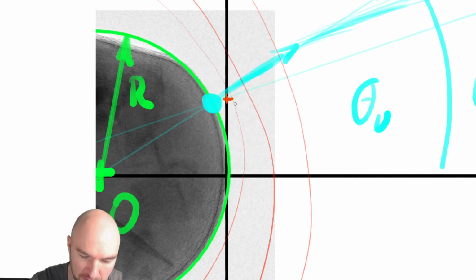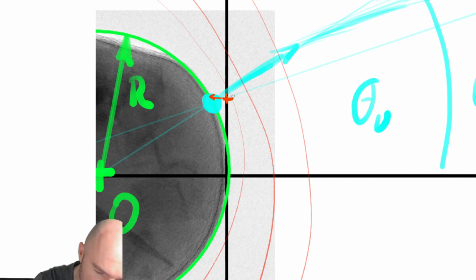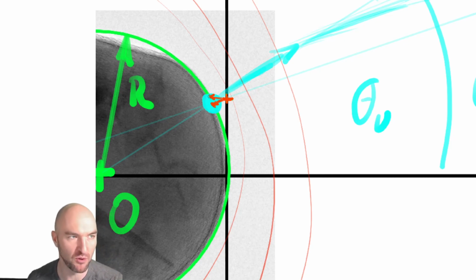Originally we just moved our atom here. In the olden days of non-wide angle atom probes, all you did for the Z correction was actually put your atom right here. This is not actually correct for any angle that's further out. If you had an old atom probe and you might just cover the bit from here to here, then that's not actually a bad approximation. But on a modern atom probe, we actually put the atom following that vector here. And this is the difference between a wide angle reconstruction and a small angle reconstruction.